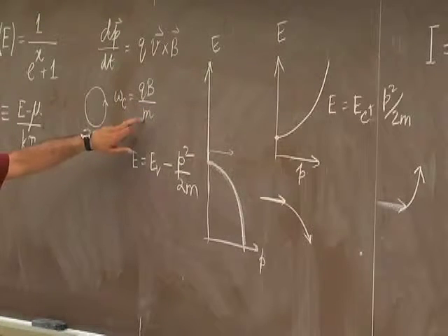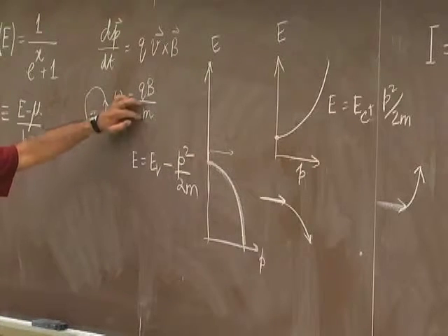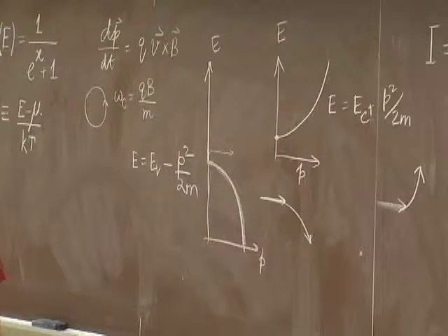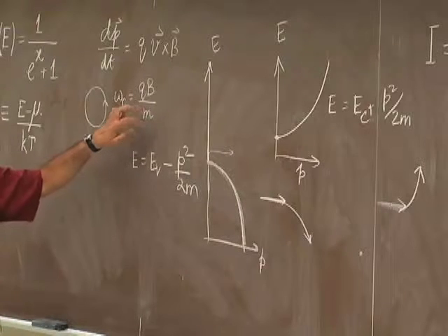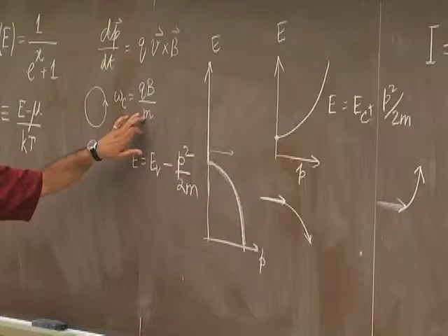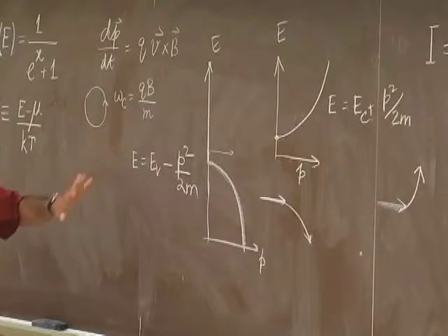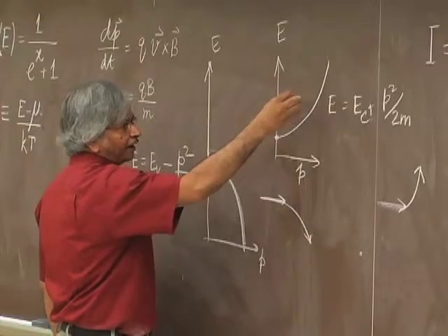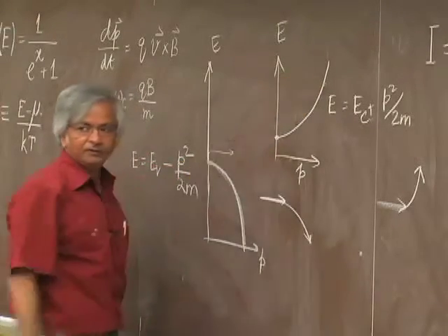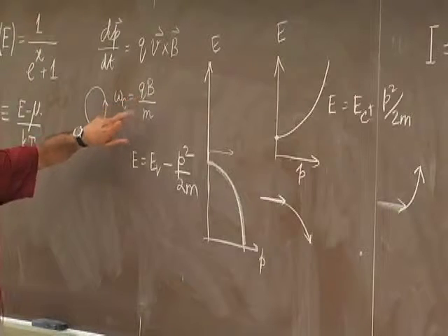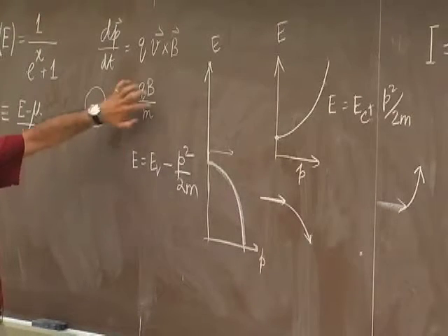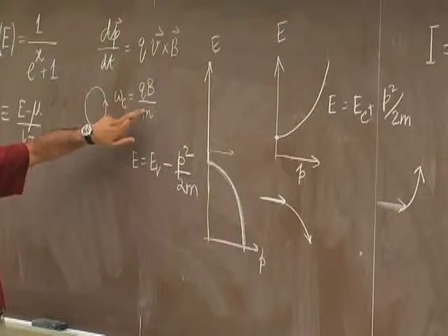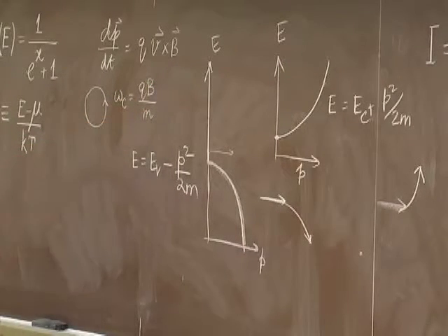And of course, when you're interpreting this, this M is like the ratio of momentum to velocity. For example, as I mentioned, in graphene the mass actually increases with energy. That's experimentally observed: when you do this in graphene, as you have higher and higher carrier densities, the cyclotron frequency actually changes, whereas usually in ordinary materials this is fixed. It's very carrier density dependent in graphene because that mass is energy dependent. As you go up, the cyclotron frequency gets smaller.